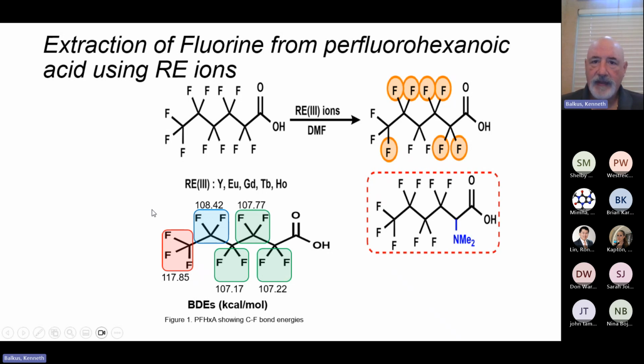And we've already pointed out that we think solvent is critical here. We seem to have some NMR evidence of having dimethylamine bound to the acid. Now, what we do is we'll do a reaction and we'll take the fluorine NMR. And we don't have model compounds, so we try to model the NMR to see what we have. And again, it seems like mostly the fluorine's at this position, and then some of these other ones seem to be in lesser amounts, but they're removed as well.